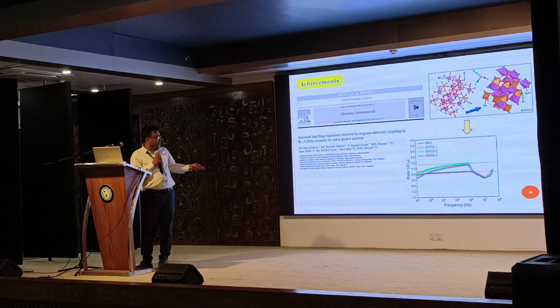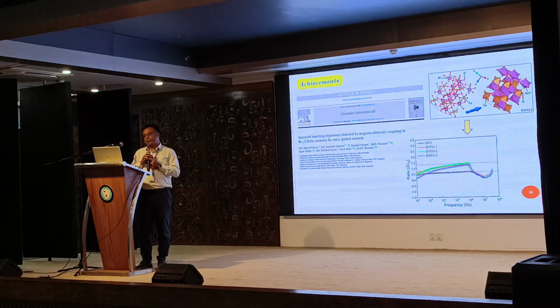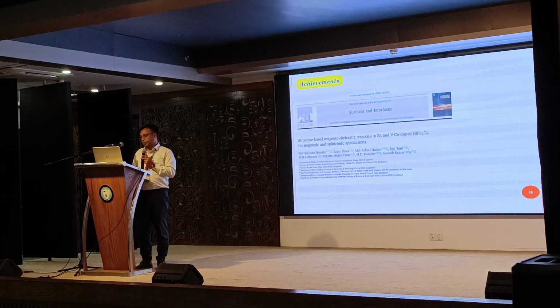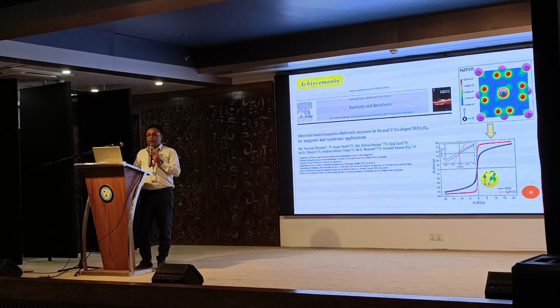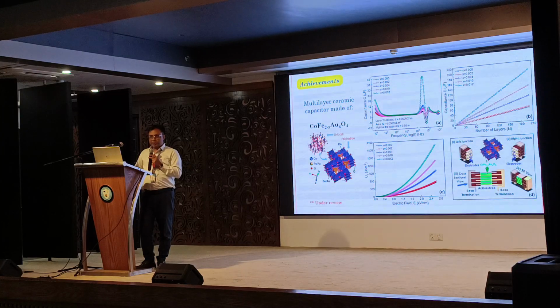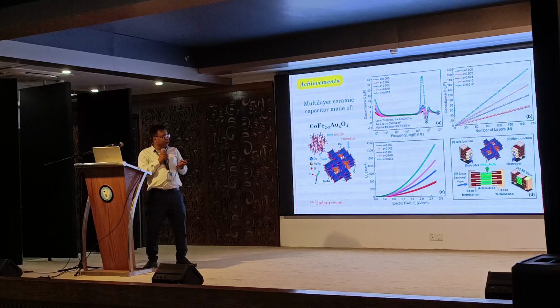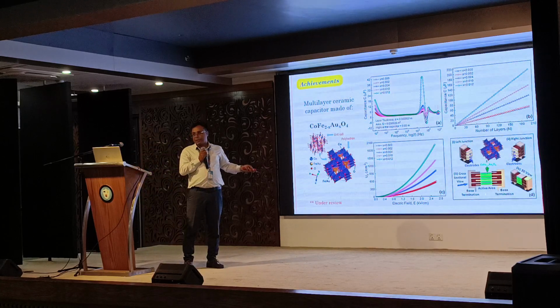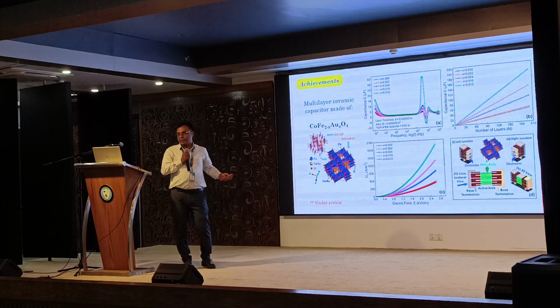These are the achievements. Previously we succeeded in the magnetodielectric coupling, but it reached more than 1, and it was not stable. Stable matching impedance we found for cobalt ferrite, gold doped cobalt ferrite. This is another success, our nickel ferrite that is doped with zinc and vanadium. We found that this is applicable for spintronics applications. This is the latest work. In our last work, we implemented it as a multilayer ceramic capacitor. This also we are making inside our lab.